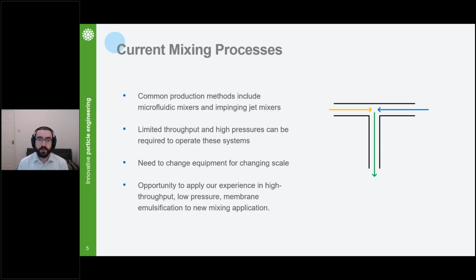Some of these systems can also take very high pressures as well, and that can make process controls difficult. You're trying to constantly manage these two high pressure pumps that are blasting against each other, which can be difficult for those control procedures. It can also introduce quite high shear as well, and when you're handling mRNA, which is quite a sensitive molecule, those high shears are not necessarily desirable for this sort of process. You can also need to change equipment for different scales. So at small scale, you might be working with microfluidics on your benchtop. Then you have to go to a high pressure impinging jet as you get towards production. And having to do that equipment changeover after you've spent a lot of time developing your process already is not going to make anybody happy.